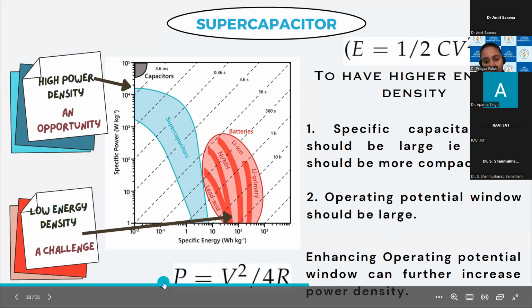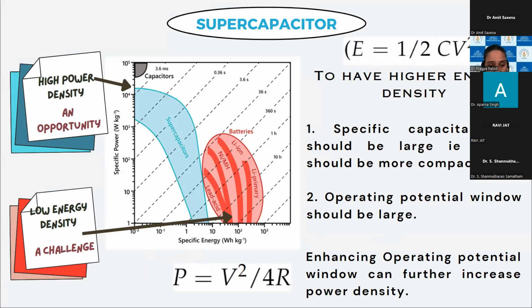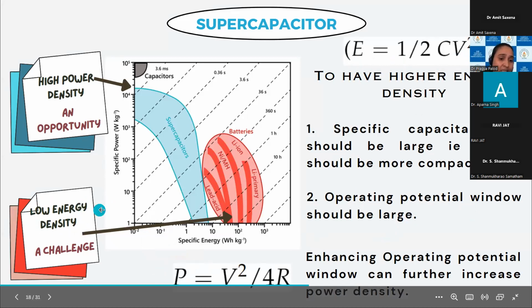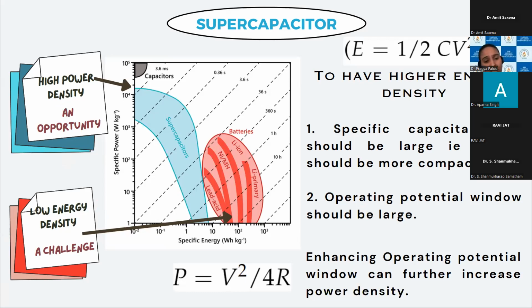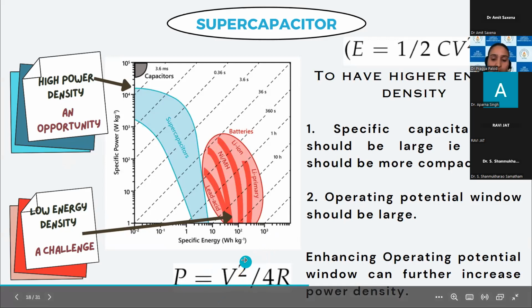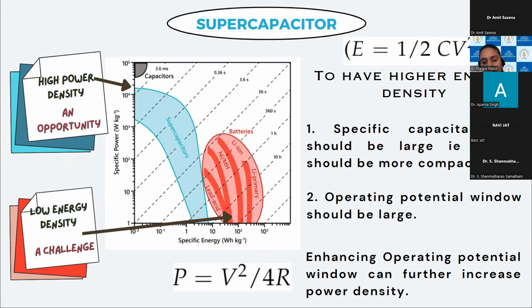And you see, power density is defined as P is equal to V squared by 4R, where V is again the potential window and R is the intrinsic resistance. So again, you see that though our motto is to enhance the energy density, we are not bothered about the power density because that is sufficiently and satisfactorily high. But having a large potential window has a two-way advantage, that P is proportional to V squared. So enhancing the operating potential window can further increase the power density. So that's the key point one should fetch if somebody is looking for working in the field of supercapacitors or to design the electrode or electrolyte materials which can support the supercapacitor's efficiency. Then one should look at those materials which have suitable capacitance values and potential windows.